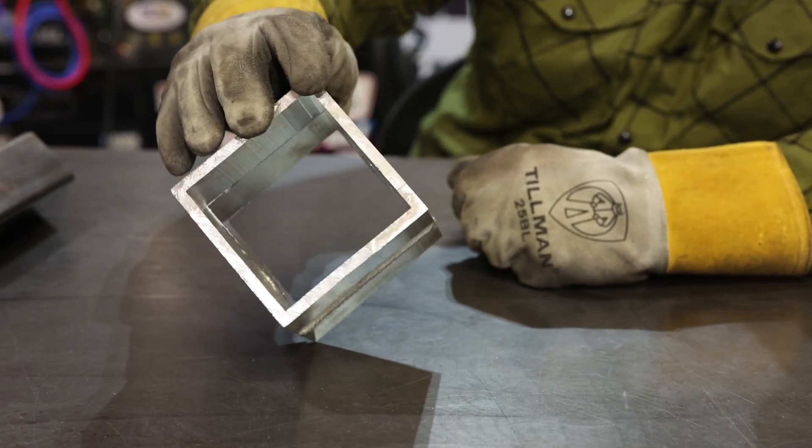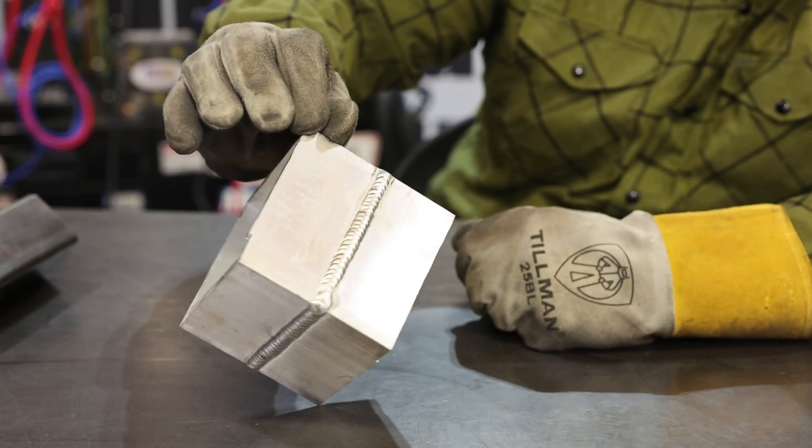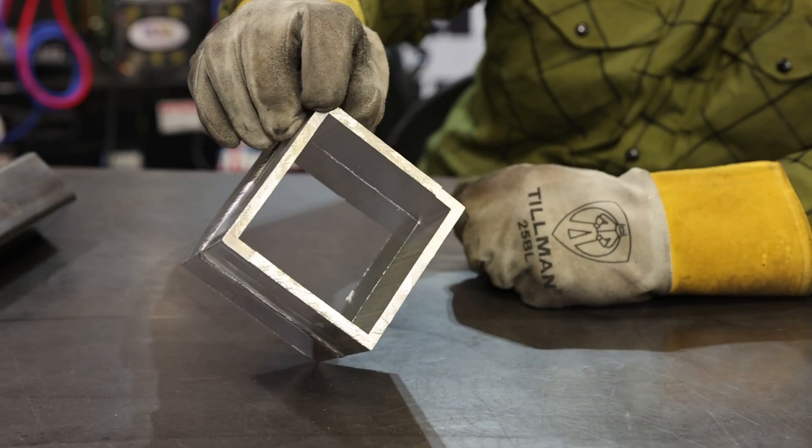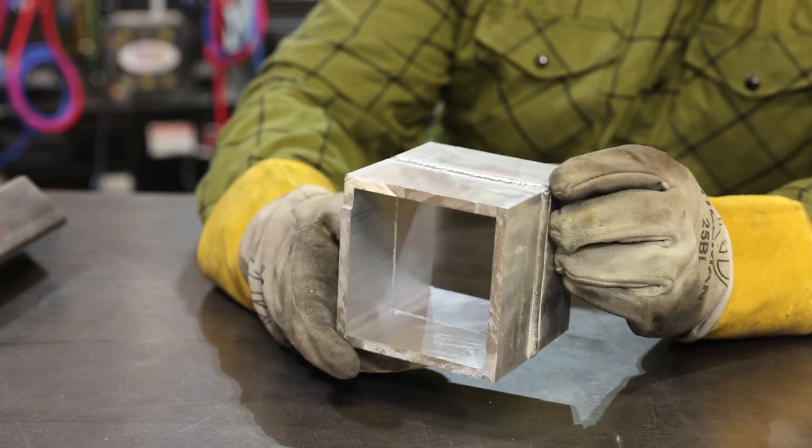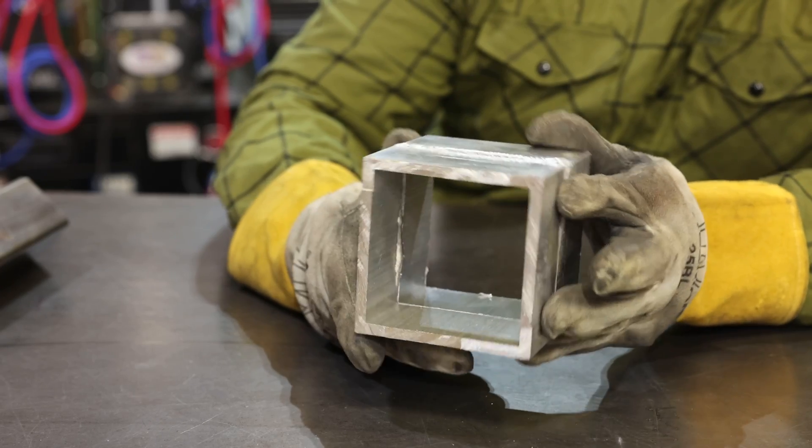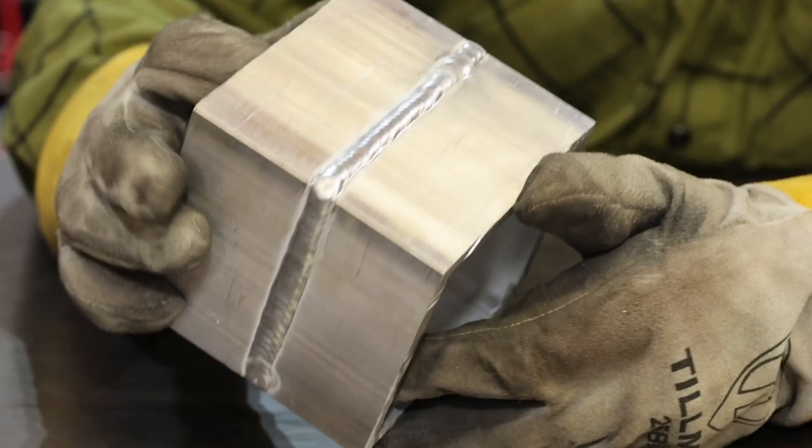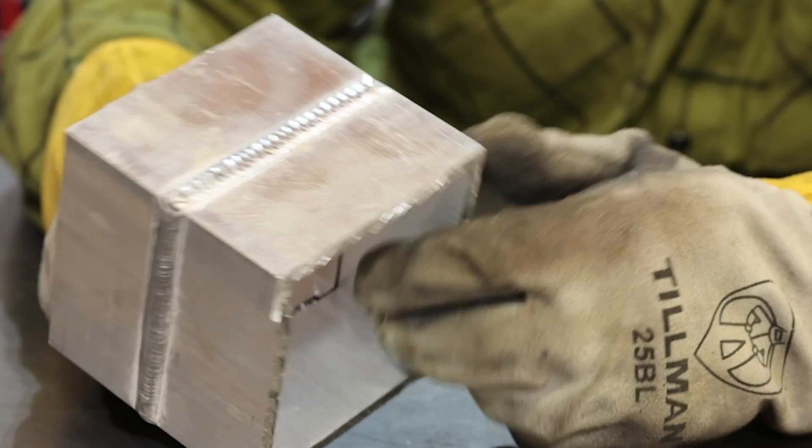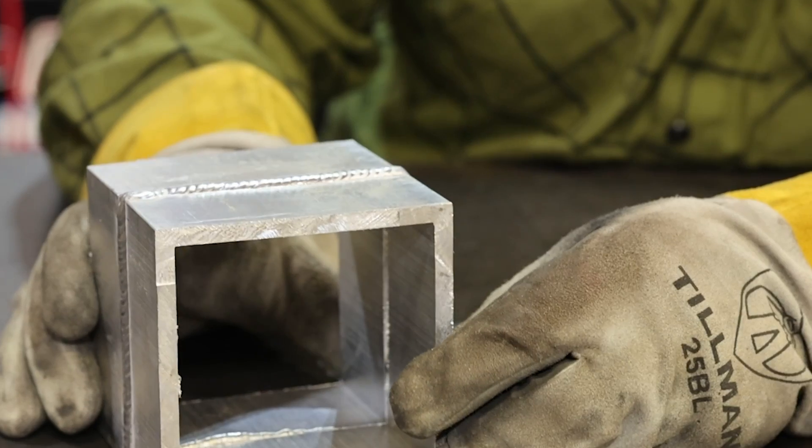Alright, here's the top sides. You can see this is the regular AC. It's much colder. They're a little bit shinier just because we are getting a lot more of that cleaning action. So it is a cleaner weld than the advanced AC pulse, but definitely a lot colder. You can actually see inside the cube here. We ran one bead here of the advanced AC pulse just to give a real good side by side. But this material was already heat soaked from that advanced AC run we did. And then we did three more regular AC runs and still no penetration. We even opened the gap up. I don't know if you guys can see this on camera. We really opened this gap up and still couldn't get it to burn through. So definitely a lot colder than our advanced AC pulse.